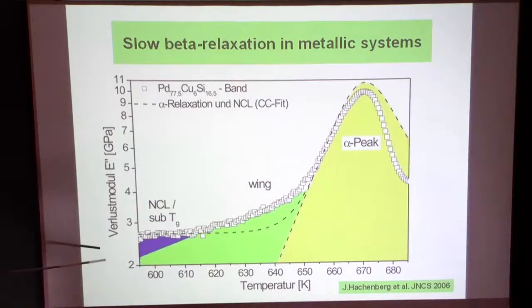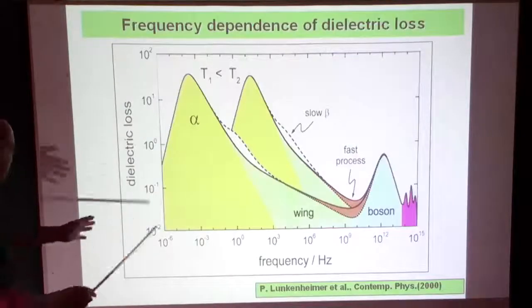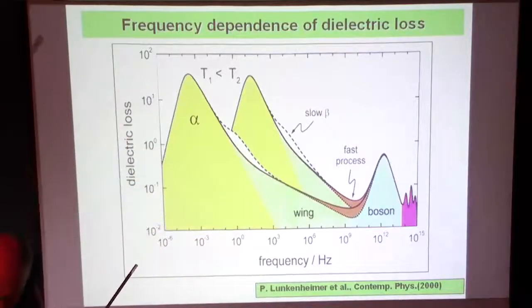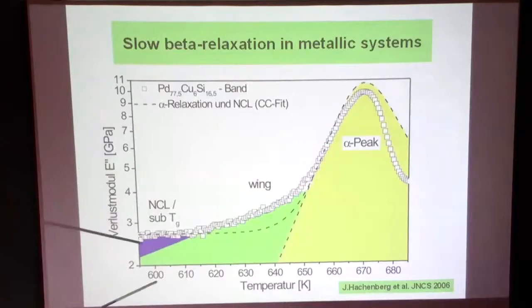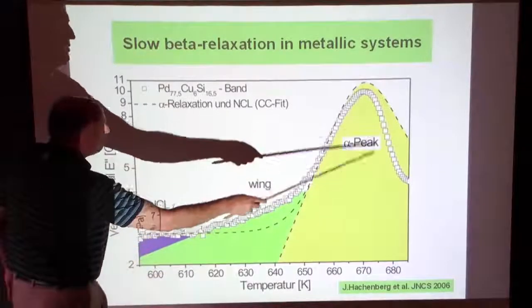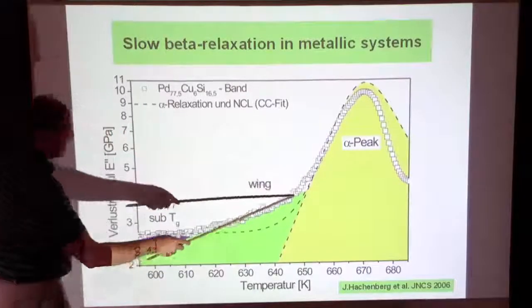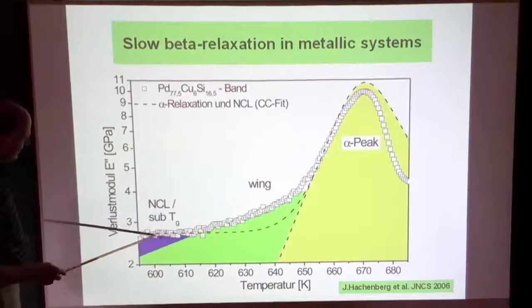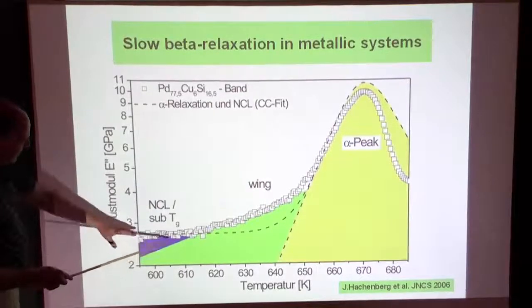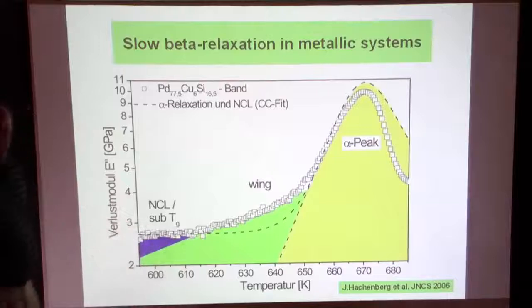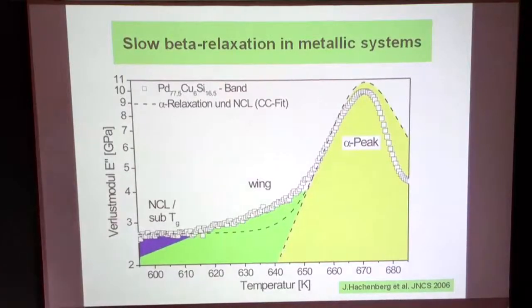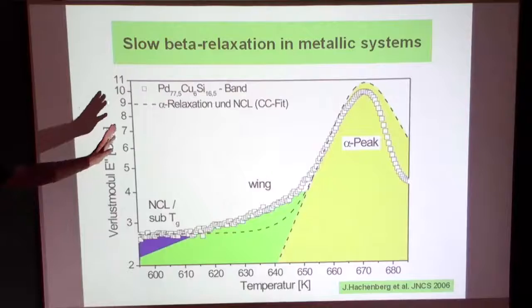Here we do have now the modulus, the loss of the modulus versus temperature. And what you saw just 2 slides before in this general picture, which is on the low frequency side, and then higher frequencies, is just turned over in the temperature domain to the high temperatures for the alpha peak. Tg is around here somewhere. You see the wing coming out down here. There are some losses. And if you measure more carefully, later on we found that the losses are getting smaller and smaller. Our frequency here is quasi-static.